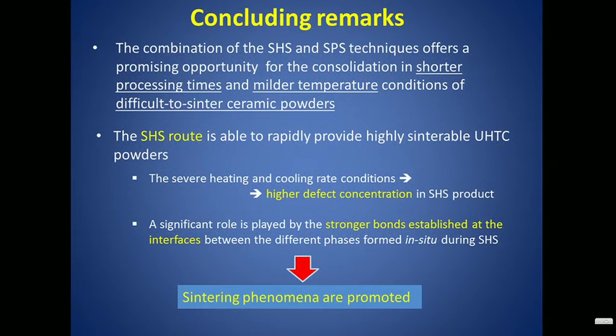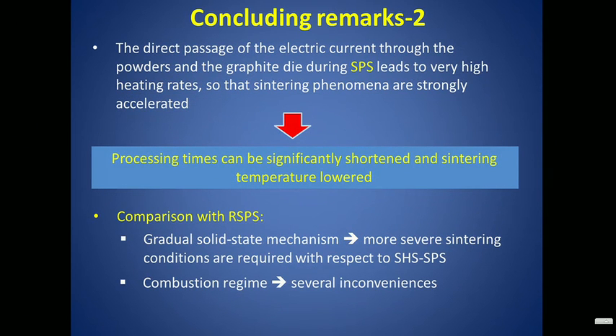So let me go to a few concluding remarks. We have been showing that if you produce the powders to be sintered by SHS, remember, self-propagating high temperature synthesis, what is good is that you get powders that are very sinterable. Powders that can be sintered quite easily, and the reason is that stronger bonds are established at the interfaces between these powders. If you look at spark plasma sintering as a potential technique to sinter this material, at the very end you get shortened time and lower sintering temperature, and this of course is a reduction of costs.